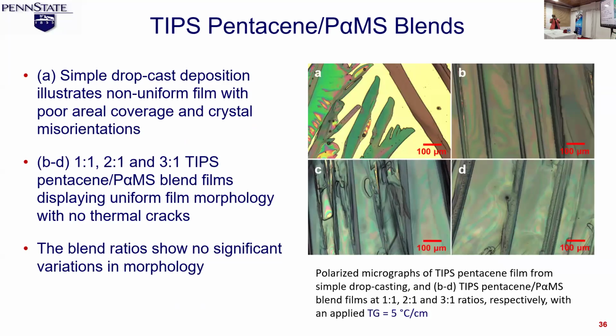So again, using the same temperature gradient method, the images that we see here are polarized optical images. Image A is just a simple drop cast, again, not using the temperature gradient method. And then B through D were with different amounts of polymer added to the semiconductor. So B was 1:1, so 1 part semiconductor, 1 part polymer. C, 2 parts semiconductor, 1 part polymer, and then D was 3 parts semiconductor, 1 part polymer.